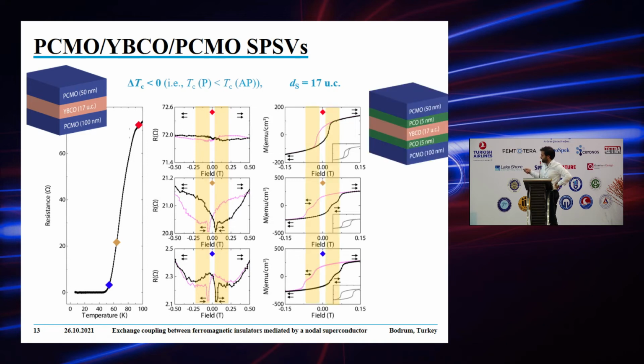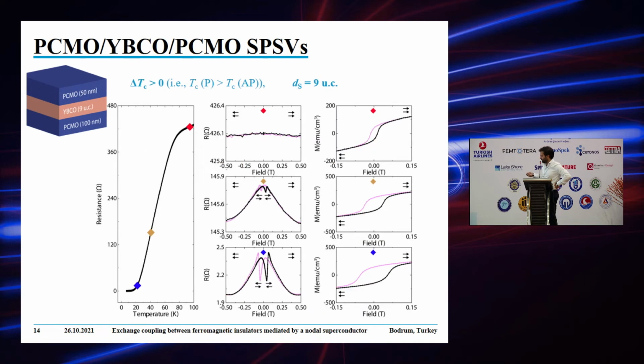To prove that this was due indeed to a proximity effect, what we did then was to insert an insulator between the two sides. So PCO is an insulator, and in this case, these magnetoresistance features did not appear, and the MH loops are just sigmoidal. So you can see that there is no increase in this antiparallel region, if you want, from the MH loops.